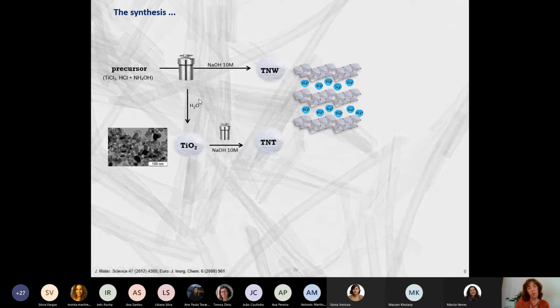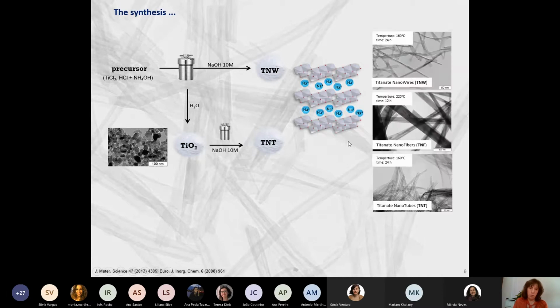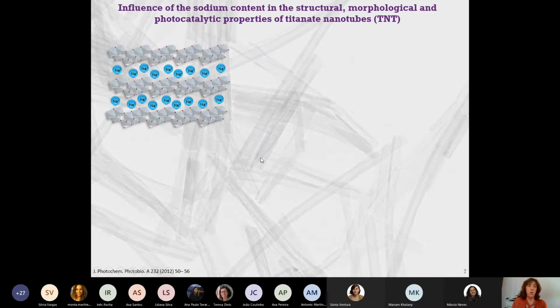Or if we decide to use water as solvent, we will have anatase nanoparticles that then can be used to prepare titanate nanotubes. And just to have an idea, playing with the time and temperature of this process, we are able to control the morphology of these materials. We can have nanowires, nanofibers, or nanotubes. So this is the structure of our titanates.